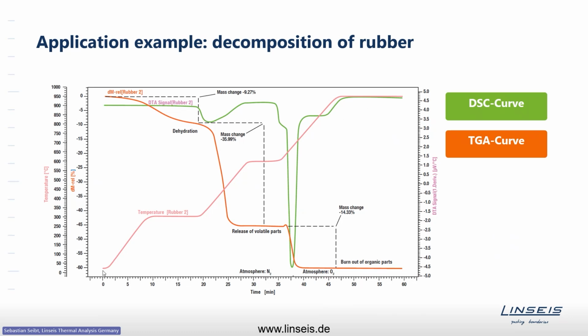What was done here was the sample was heated to the first isothermal segment, roughly at 300 degrees Celsius. During heating and during this plateau, there was a slight mass change, a slow mass change ongoing until reaching a plateau, a stable mass again. There was almost no DSC signal. So you can be sure that this mass change is surface volatile, surface water that just evaporated without causing a bit of heat flow change.